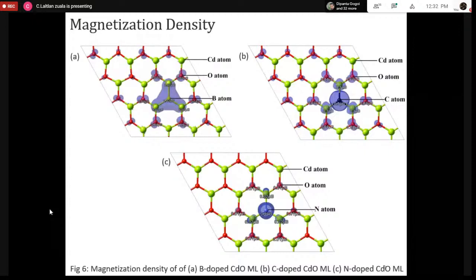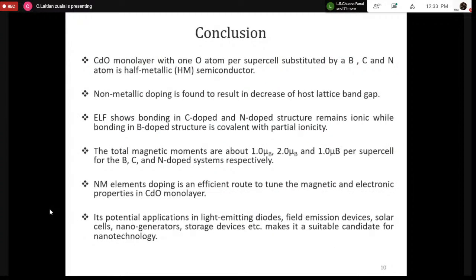Here we have the magnetization density calculation. It shows that the magnetic moment arises mainly from the dopant atom, which is boron, carbon, or nitrogen. It induces a magnetic moment in the nearby atoms, the Cd and oxygen neighboring atoms. You can see from the figure that the B atom possesses a local magnetic moment of around 0.12 μB, C possesses around 0.5, and nitrogen possesses around 0.4 μB. This magnetic moment arising from the dopants changes the non-magnetic system into a half-metallic magnetic semiconductor with a total magnetic moment of about 1 μB for the boron doped, 2 μB for the carbon doped, and 1 μB for the nitrogen doped CdO monolayer respectively.